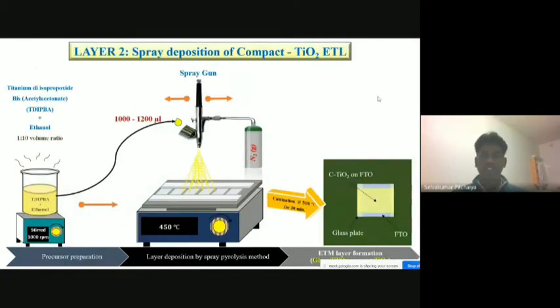And this is the first layer, the compact TiO2 layer. As I said, it needs a transport layer. This is the electron transport layer. For depositing it, we followed a low-cost deposition approach. Spray deposition is a huge unit, and it needs a lot of energy, power supply, and vacuum conditions. But here we are using just a brush painting, spray painting technique. This costs around 500 rupees in our country. We have taken this for our lab experiments, and we sprayed to and fro over the substrate, and we annealed the layer so as to form the TiO2 structure over the FTO plates.